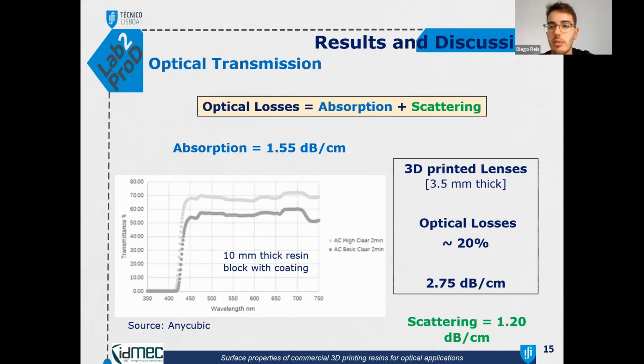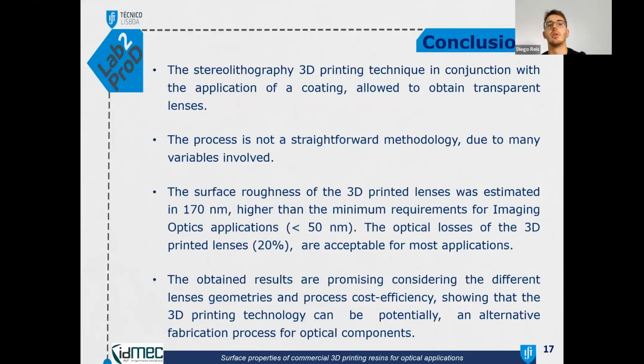It is also reasonable to say that this percentage of optical loss is acceptable for most optical applications. To conclude, stereolithography with the dip coating technique allowed us to obtain transparent lenses. It's not a straightforward methodology due to the many variables involved. The surface roughness was a bit higher than the minimum requirements for imaging optical applications, but the optical losses were acceptable for most applications.